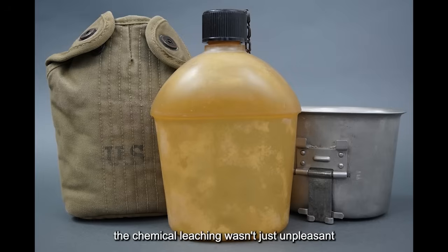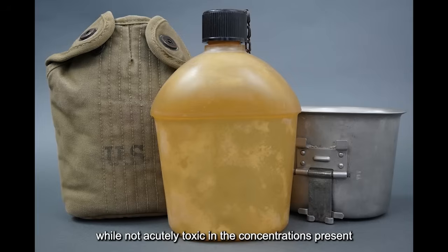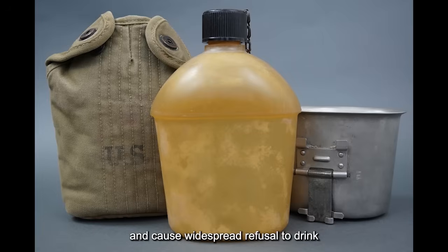The chemical leaching wasn't just unpleasant. The bitter taste came from residual solvents, plasticizers, and unreacted monomers trapped in the polymer during manufacturing. While not acutely toxic in the concentrations present, these compounds were enough to trigger nausea in many troops and cause widespread refusal to drink. This was the fatal flaw in the American approach. By trying to eliminate metal entirely, they put drinking water in direct contact with a material that wasn't chemically stable enough for the application. The Germans kept their aluminum liner specifically because it was inert, proven, and safe. The Americans tried to skip that proven solution and paid the price.